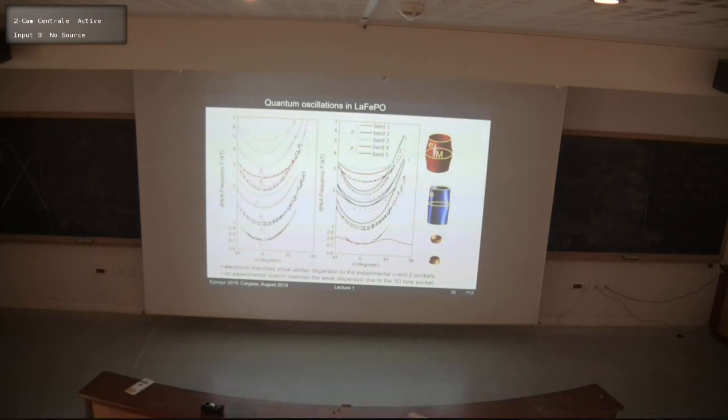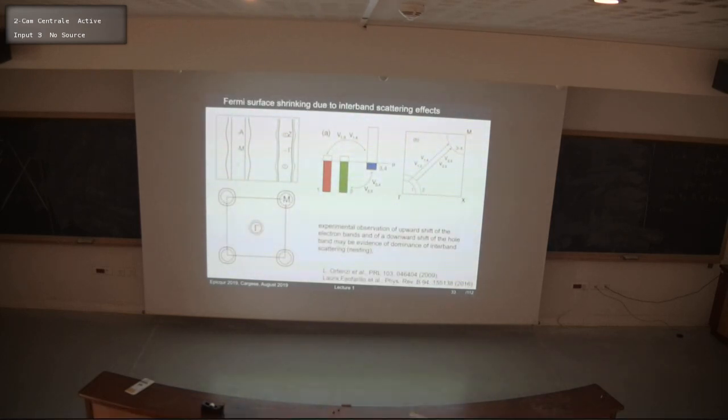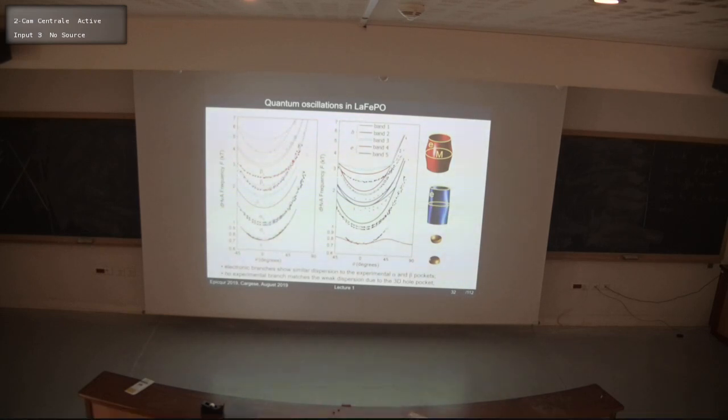And that's why we also know that this comes from the same orbits. But what I wanted to emphasize here was that we have band structure and data, and in this particular case we should have a straightforward, reasonably good metal. All the band structures overestimate the real data. If we look at the real data here, the calculations give us bands which are slightly heavier, larger compared with experiments. And also this particular band we don't seem to see.